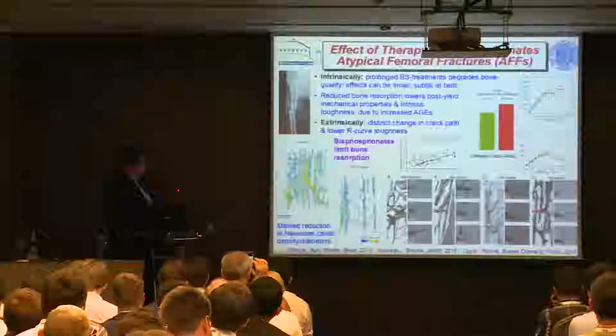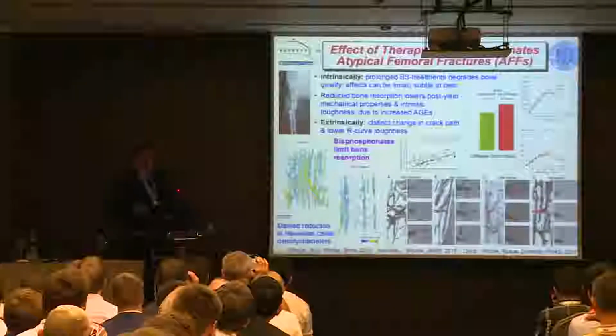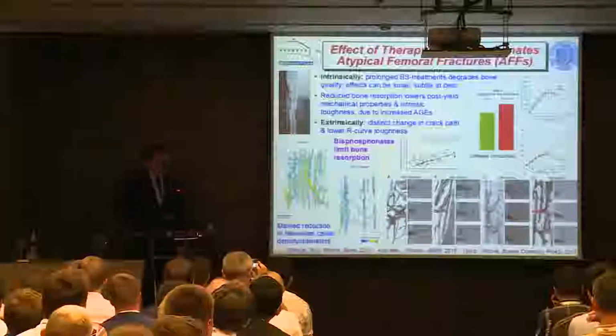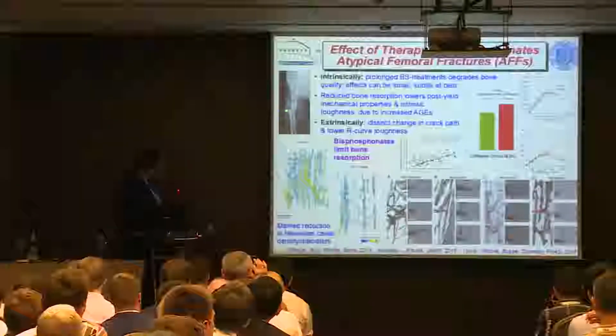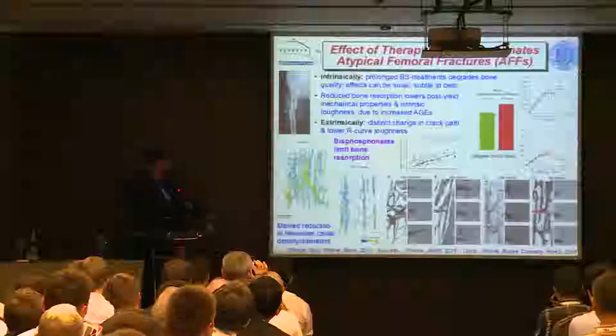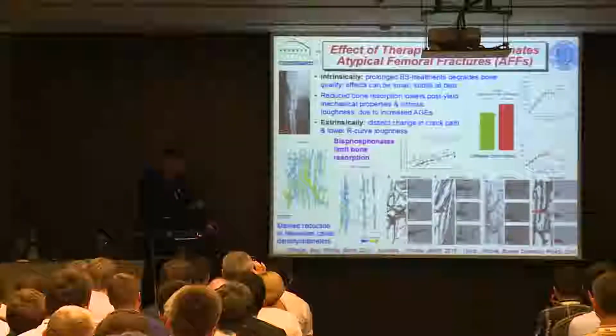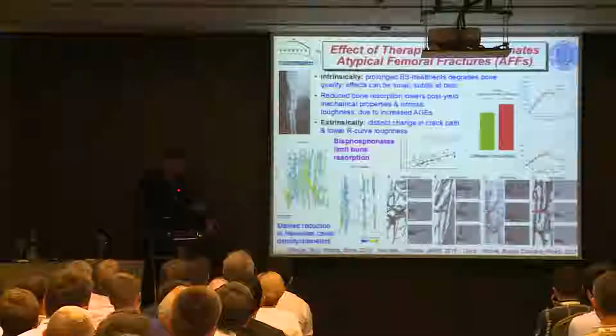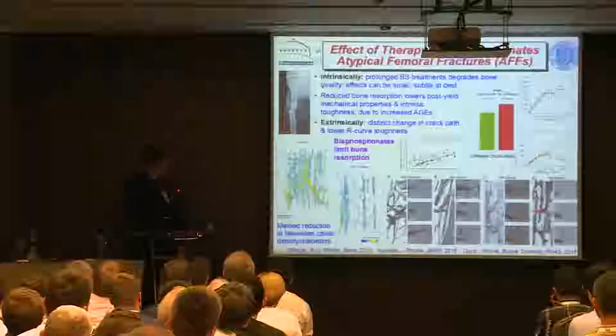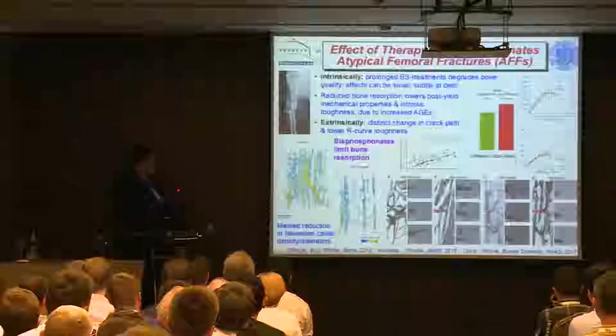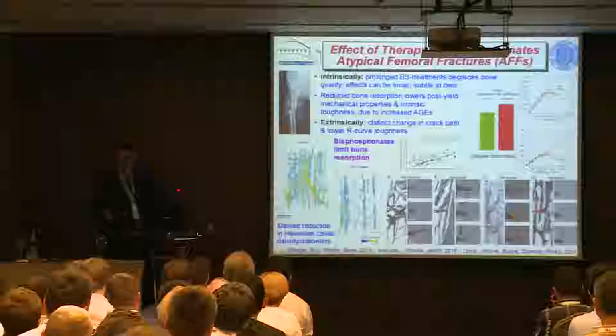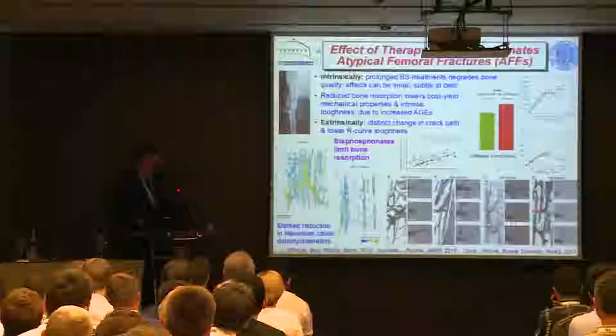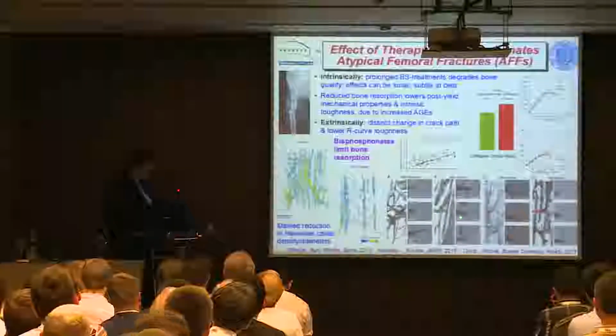And this is a great shame, because these are good drugs. So we've been trying to understand what this is caused by. You'll notice this fracture is very, very clean. If you broke your arm now, you'd have a really jagged fracture as the crack tends to deflect along the osteonal boundaries. This is very, very clean, and we've just recently been able to get bone from people who've suffered these fractures, and you can see what happens here.